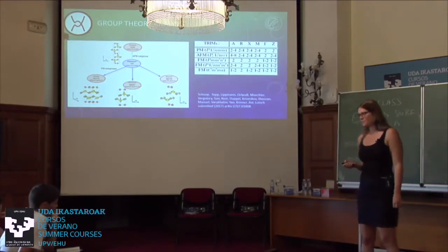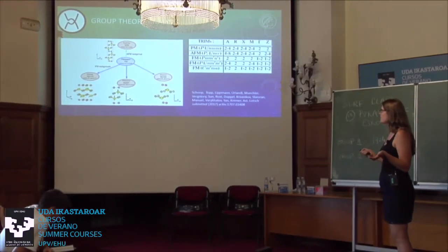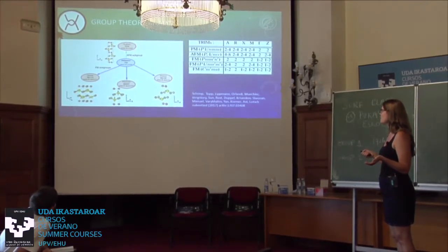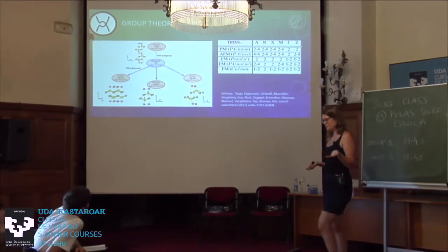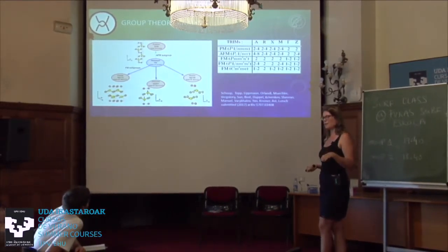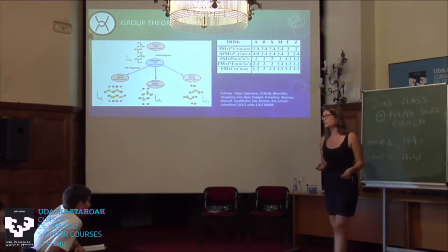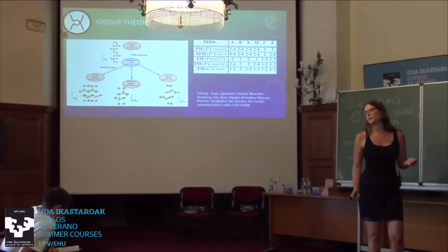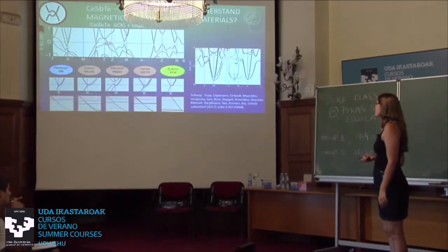And once we realized that, it actually makes sense to us because we double the C-axis in this magnetic order, we add another non-symmorphic symmetry element here. You see this kind of translational symmetry with the spin coming up here. So we basically stumbled across the fact that we can use antiferromagnetic order to even add non-symmorphic symmetries to materials where they were not there before.